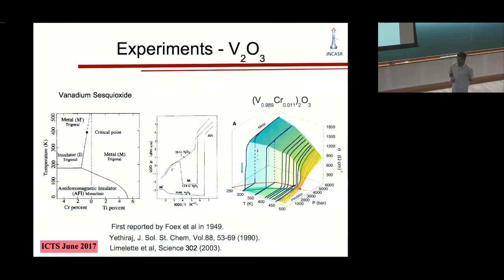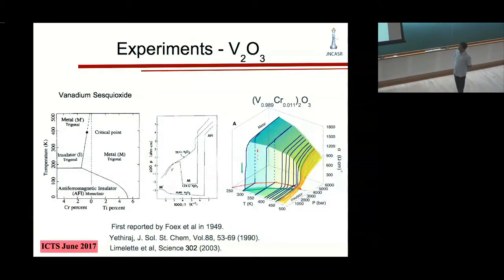Okay, so these are some of the old experiments on the Mott transition. This is a classic system, vanadium sesqui oxide, V2O3, where the phase diagram here, which is temperature versus chemical pressure, shows these three separate phases. This is a paramagnetic insulator, this is a paramagnetic metal, and it's an antiferromagnetic insulator. And these are first order lines which end in a critical point. And the transitions here are really dramatic, which you see here with log of resistivity as a function of inverse temperature. And you see many orders of magnitude change in resistivity.